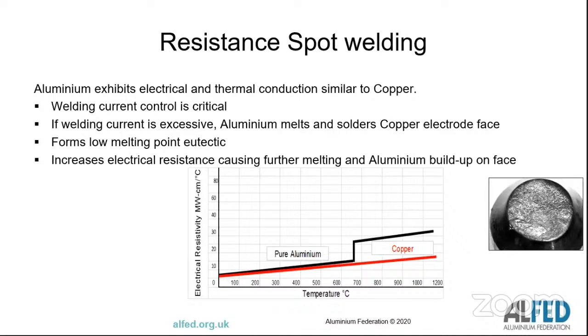Now, aluminium has got very similar thermal conductivity to copper. And that means that up to its melting point, the two have got almost a straight conduction line. Once aluminium melts, the resistivity increases, but that of copper carries on a straight line. So if we're not careful and we allow the welding current to run away, we'll end up with excessive welding currents. The aluminium will melt and it will solder the copper electrode. And what will happen is we'll form a low melting point copper aluminium alloy on the face of your spot weld.